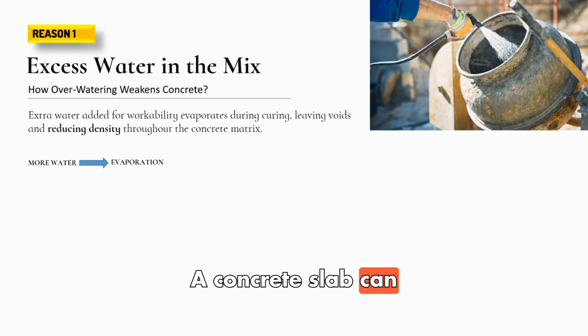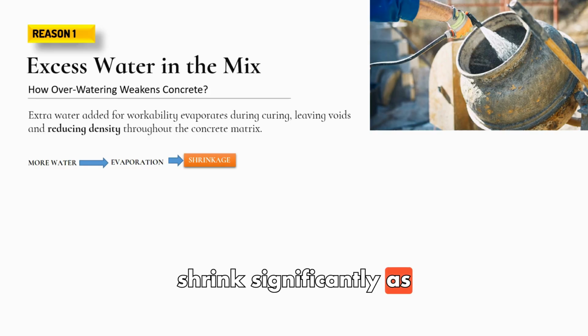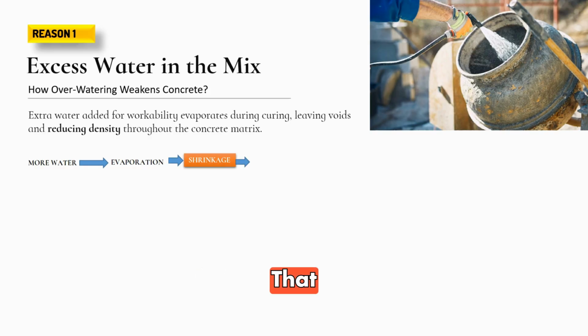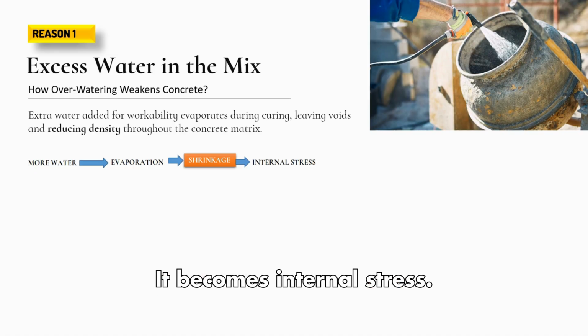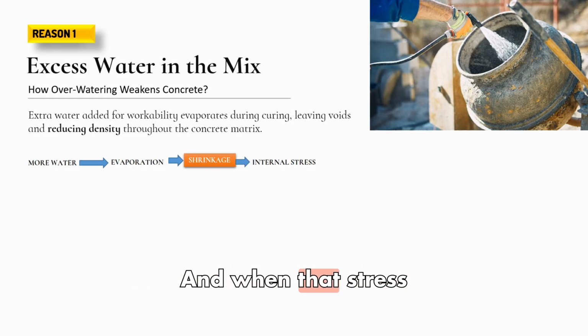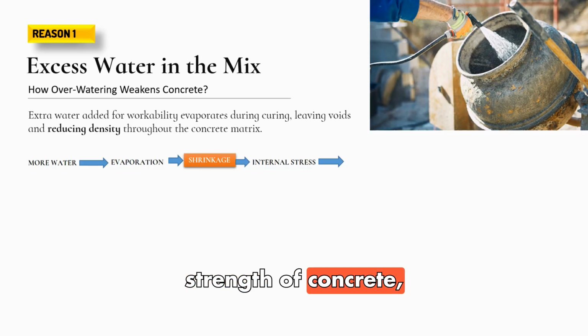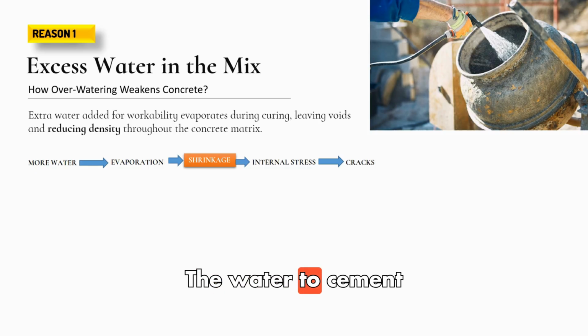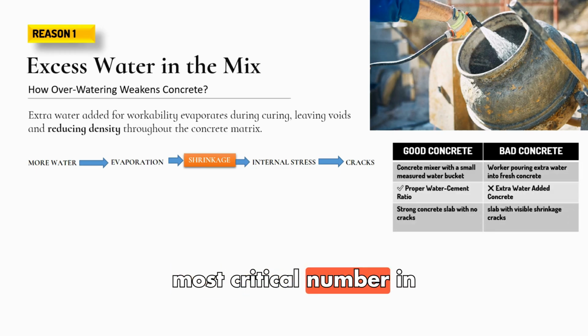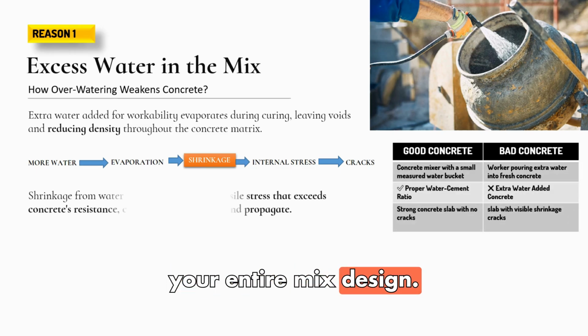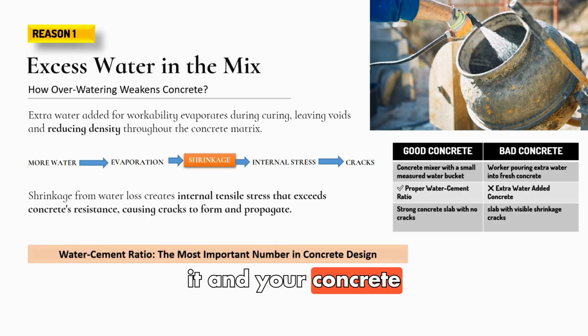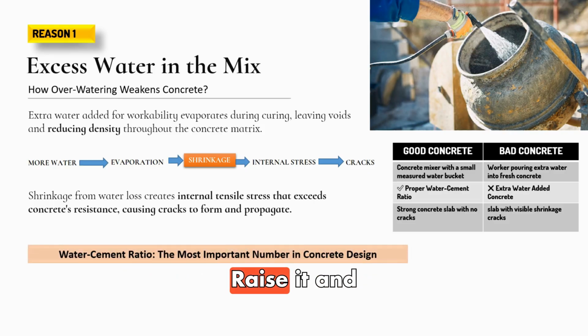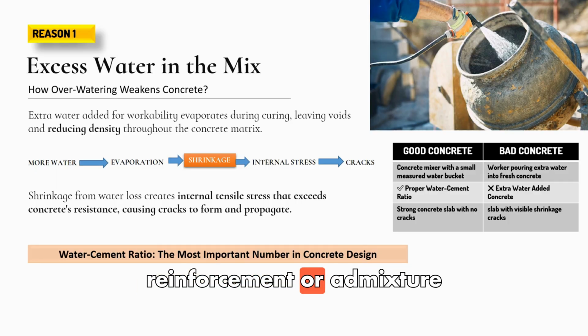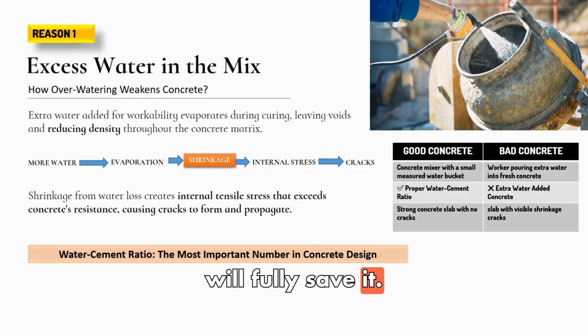A concrete slab can shrink significantly as it dries and cures. That shrinkage does not disappear. It becomes internal stress. And when that stress exceeds the tensile strength of concrete, a crack forms. The water to cement ratio is the single most critical number in your entire mix design. Lower it and your concrete becomes dramatically stronger. Raise it and no amount of curing, reinforcement or admixture will fully save it.